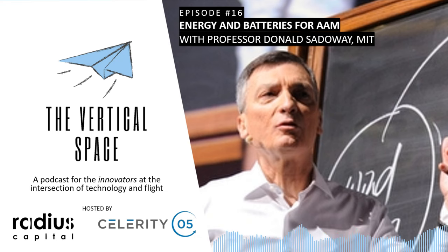And the liquid metal battery, as the name implies, has liquid metal electrodes, and it has a molten salt electrolyte. It's a three-layered system. Just think of salad oil and vinegar, only instead of two layers, we got three layers. So we got a low-density liquid metal on top. Underneath that is a molten salt, which acts as the electrolyte. And beneath the molten salt is a high-density liquid metal. That's what gives you the voltage, the difference in chemical potential of the low-density liquid metal and the high-density liquid metal.